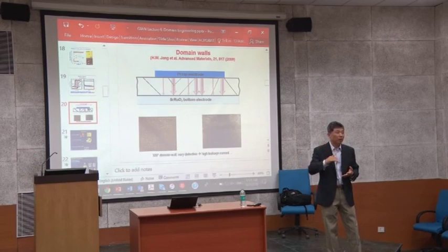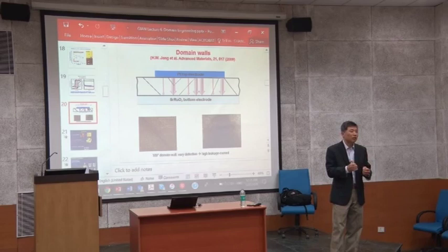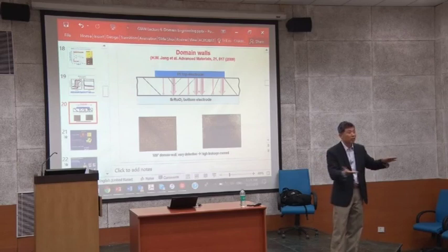Okay, so for example, in bismuth ferrite here, when you grow extremely ultra thin films, a very, very thin layer, then the substrate clamps it and it goes to tetragonal. It's a tetragonal domain, ultra thin, because strain is huge, right? Strain is huge, and it actually prevents formation of rhombohedral. It's like tetragonal. In a true sense, it's not tetragonal, it's monoclinic. It's a little bit of distortion.